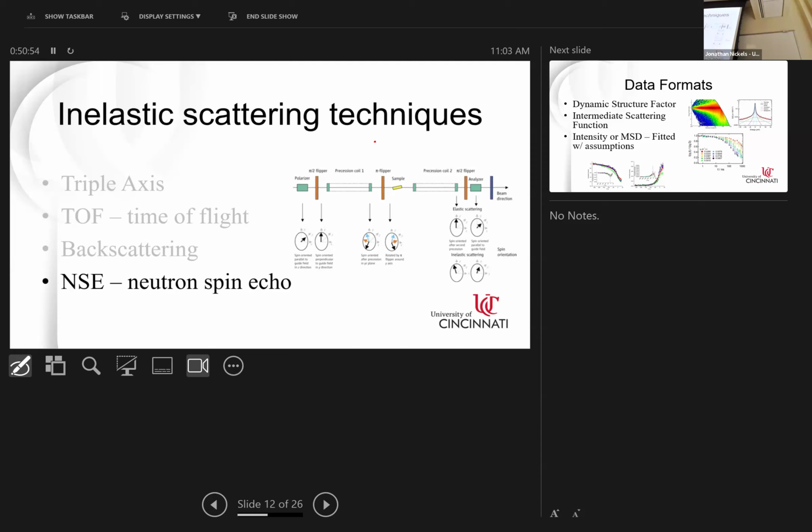So you want to design a battery, go to spin echo. That's where they're doing a lot of this research on, okay, so I want my lithium ions to be very mobile, but I want the battery to be a solid. So I have this backbone matrix that has a low relaxation rate, but I have side chains that interact with water and ions, and they're very mobile. And so you create these parts of your polymer matrix that are very fluid, and so electrodiffusion can happen. And then you still have the solid matrix there that doesn't deform. You'd be seeing the differences in those two time scales.